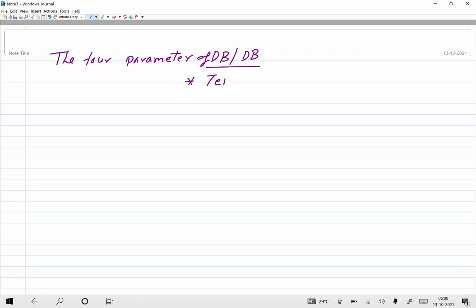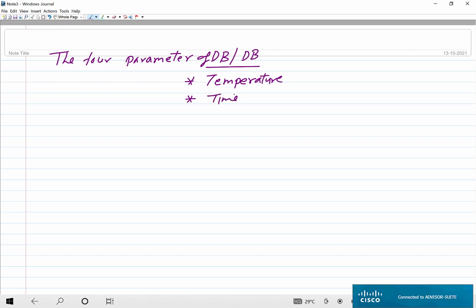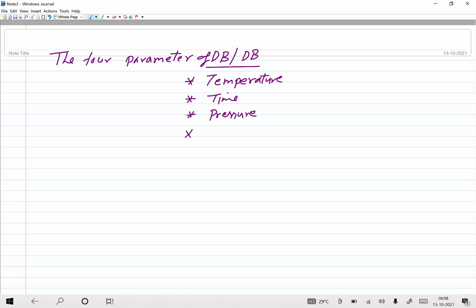These are the temperature under which the diffusion bonding or brazing is carried out. This is one. The time for which the high temperature exposure is given, second. And the pressure to ensure good metallic contact between the two components being joined is the third. And in some cases we may use a filler or films for controlled alloying at the interface in order to achieve the desired objectives of lesser bonding time, good metallic contact between the two components being joined, and reduced diffusion time, because some of these alloying elements also act as a diffusion accelerator.